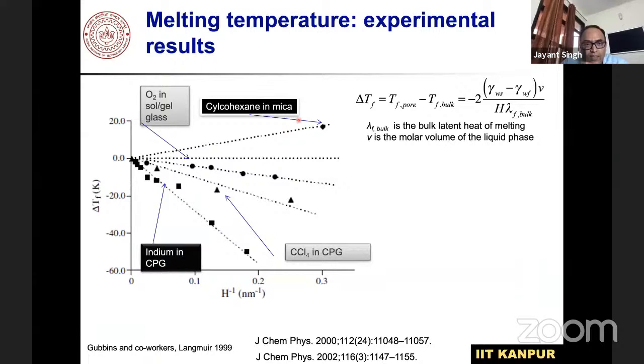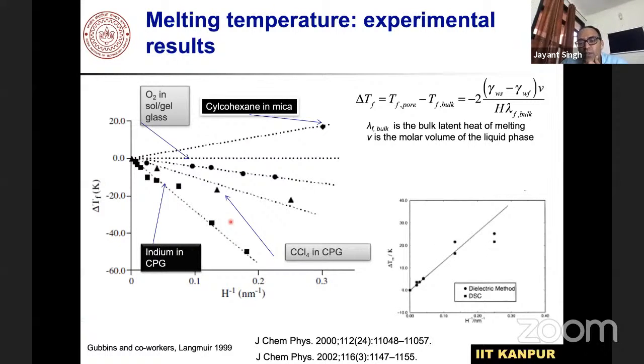The positive and negative slope is related to the strength of the material. Mica, being very hydrophilic, had a positive slope, whereas the other materials were hydrophobic in nature. Anyway, when we looked deeply, we observed that there is some kind of fluctuation, occurring at a very small scale, a few nanometers, less than 10 to 20 nanometers. This bothered us, like maybe something is going on.